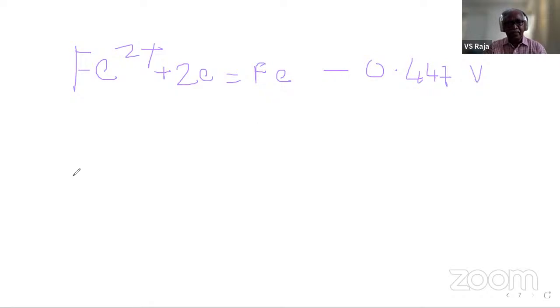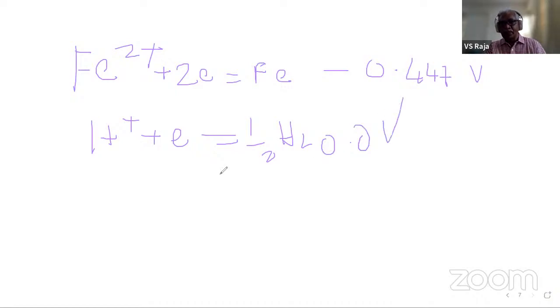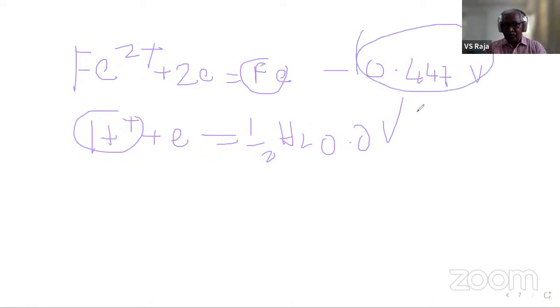Standard potentials. Okay. Now, suppose I say acid, you have H plus plus electron gives you hydrogen, and again it's a standard state. It becomes 0, is a potential that we talk about. When you immerse iron in the acid, what happens? Now iron gets oxidized and hydrogen gets liberated. In that case, you don't get this potential, nor do you get this particular potential. You get a potential dictated by the kinetics of metal oxidation and the kinetics of the hydrogen reduction reaction, right? So that's why it's called mixed potential theory.